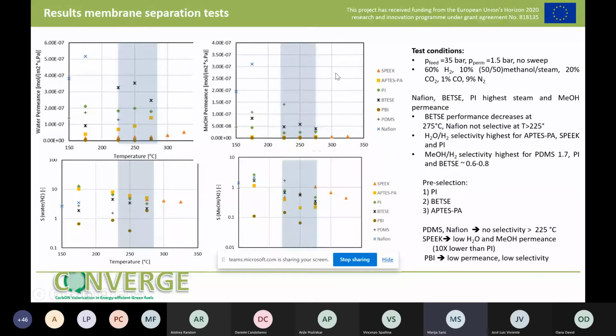What you can see in these figures in the first line are the water and methanol permeances. If you look at the membranes, we can see that the Nafion in blue crosses, the black ones, also the stars, and the PI membrane in green have a higher steam and also methanol permeance. We see also that the membrane performance decreases at 275. But also the Nafion membranes, these 2 blue crosses, we didn't test above 225 because we observed a loss in selectivity of these membranes.